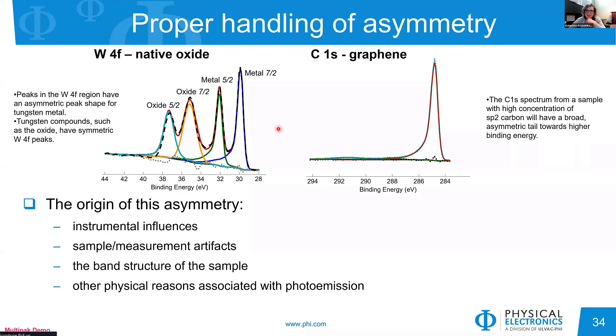The right way to fit is to include asymmetry for your metal. For tungsten, you then see two chemical states: metal and oxide. For graphene similarly, use an asymmetric shape towards the high binding energy range with fixed asymmetry parameters, then add any oxygen-related peaks that you also detect. It's really important to include asymmetry in core fitting, especially when working with transition metals.